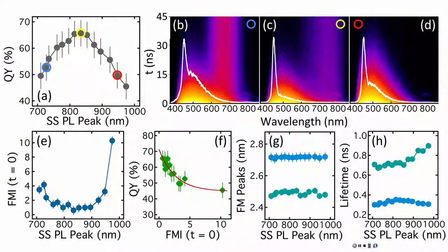Yes, but we are in the transition region between small nanostructures, which are very confined, where the word band structure is not applicable, and bulk, where the band structure picture is legitimate. We are in the transition region, and there is a controversy. There is no agreement that we can use the language of the gamma point or X point for nanostructures at all. NRL uses it all the time. It's controversial.